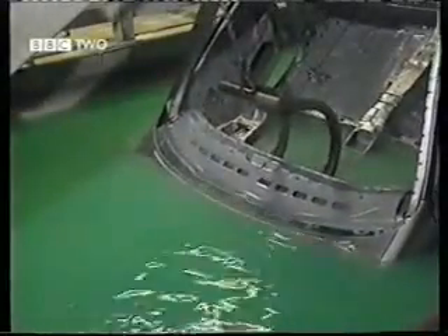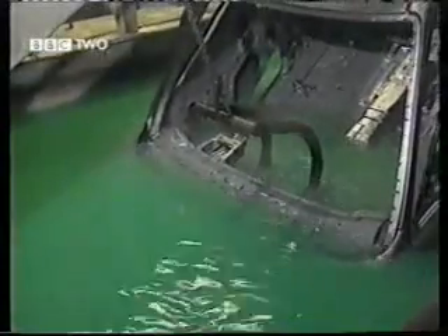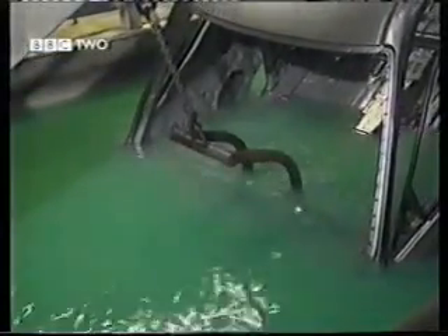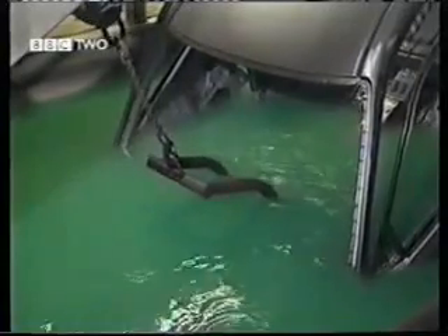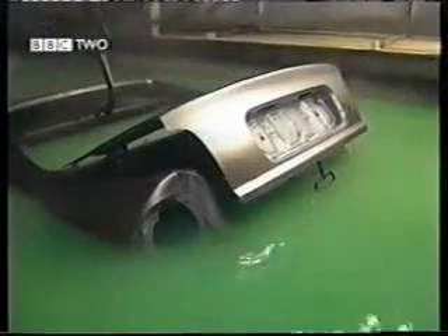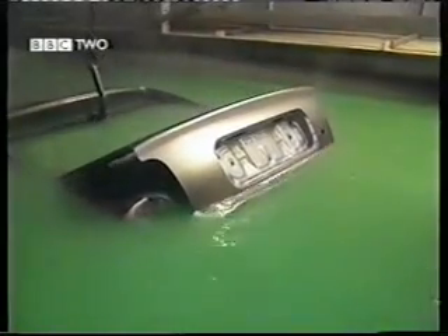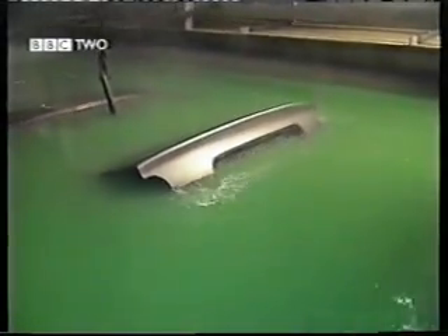The body in white emerges covered in minute crystals, which are going to act as nuclei for the climax of the process, full immersion in a tank containing zinc, manganese and nickel phosphate, and an oxidizing agent. Here, the object is to coat the metal with a crystalline phosphate in a product hopefully looking like this, and in a layer up to 3.5 microns thick.